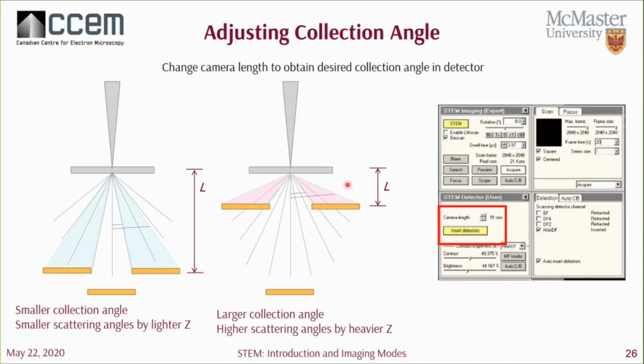So in our system, it's basically just done by the click of a button in the upwards or the downward direction. A long camera length would result in a smaller collection angle, in which you could probably collect incoherently and coherently scattered electrons. Shown here, we have our inner and outer angle. But as you decrease the camera length, you can increase the collection angle and collect these high angle scattered electrons of interest, giving you your Z contrast image.